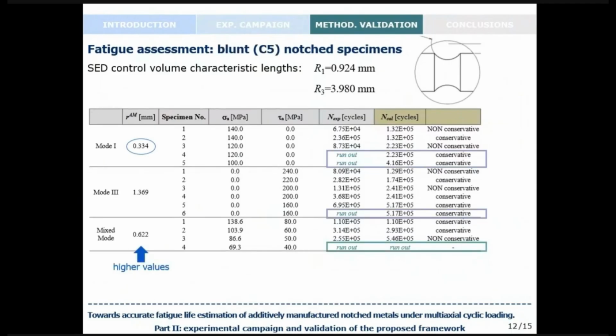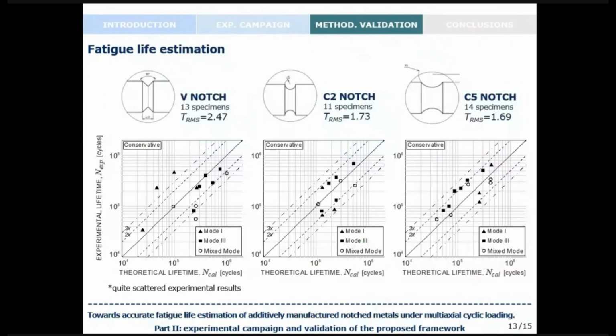And then the results for the C5 notch specimens are in line with the C2 ones, since we have similar values of the critical distance, again higher than the case of the V-notch specimens, and again conservative estimations, especially in the case of the runout tests. So here you can see the comparison between the experimental results in terms of fatigue life with the theoretical ones.